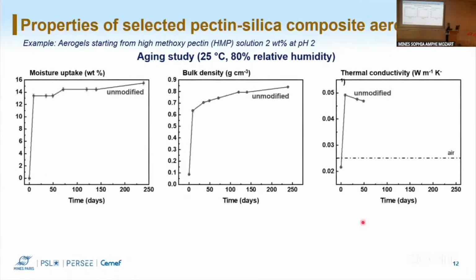In order to evaluate if our materials are stable in moisture, we do aging studies at 25 degrees and 80% relative humidity. We see first the neat pectin aerogels. As we expected, in the first day in these conditions, we have a huge increase. We have the most increase. We have moisture uptake around 15%.